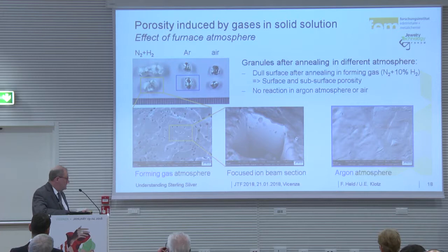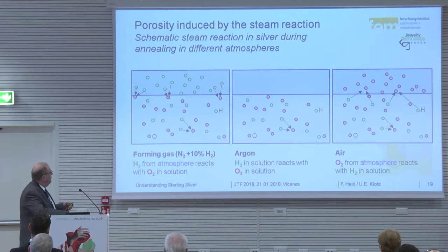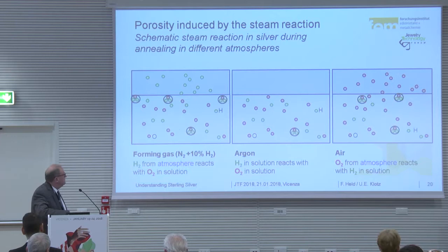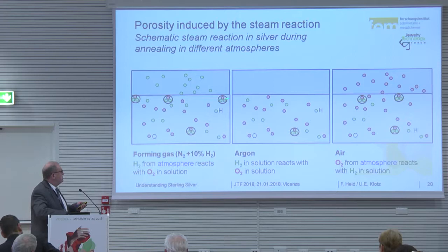What happens is, if we do annealing in forming gas, we have 10% hydrogen, and we have the oxygen in the metal. So this is metal, this is the atmosphere. If we do the annealing in argon, we have oxygen and hydrogen. If we do it in air, we also have oxygen from the air and hydrogen in the granule. This is what happens. Two hydrogen atoms combine with one oxygen atom to water, and you have the water steam because you have the high temperature and you get the bubbles in it. You also can have free gas, but mostly it is water steam. And this doesn't matter if you use hydrogen, argon, or air.